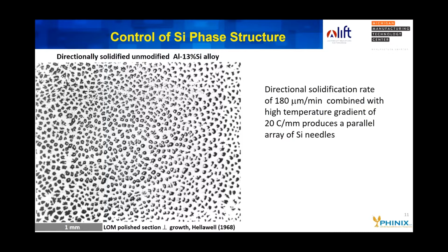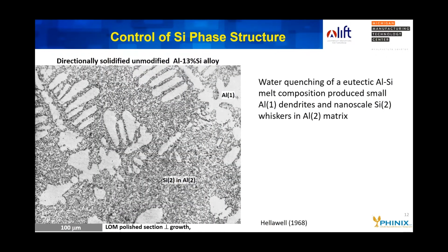In this case, you can see a nice eutectic microstructure of needles sectioned perpendicular to the growth direction, and you can see that you can get a very nice even distribution, uniform distribution of such needles. But at this cooling rate and growth rate, they are still quite coarse. When he quenched this material, in a quenched portion of the material, he got this microstructure.